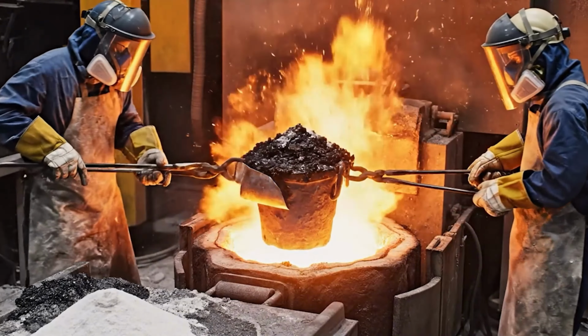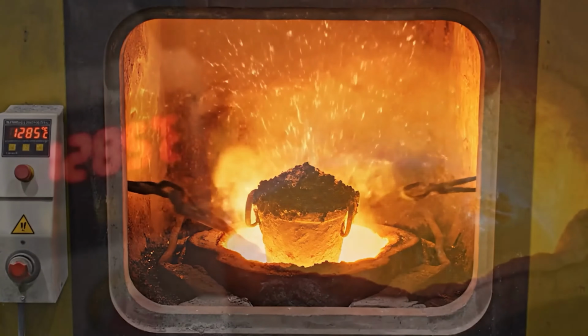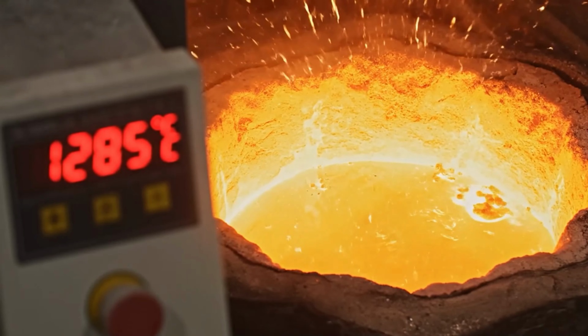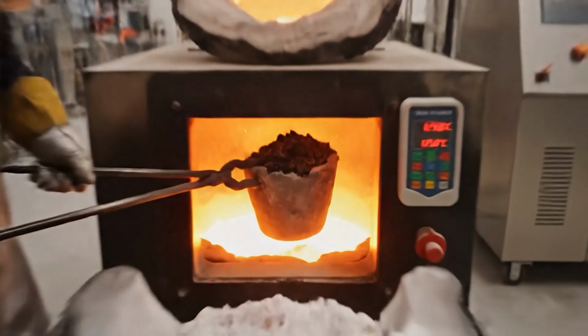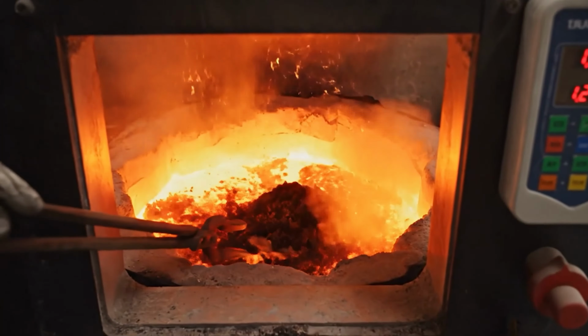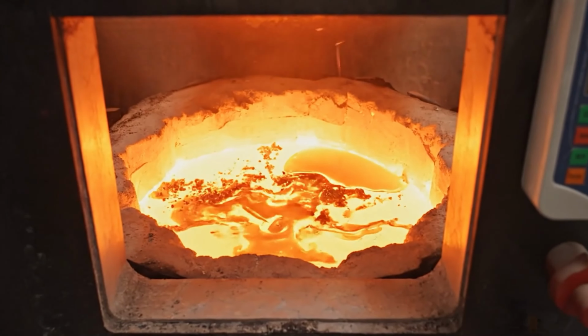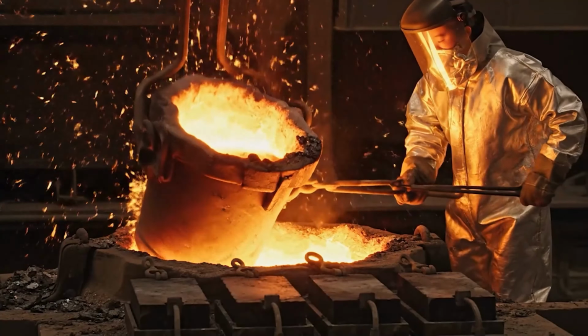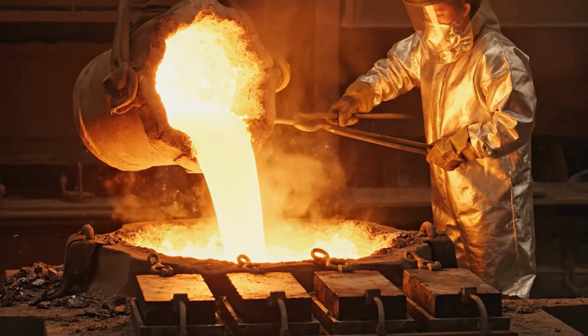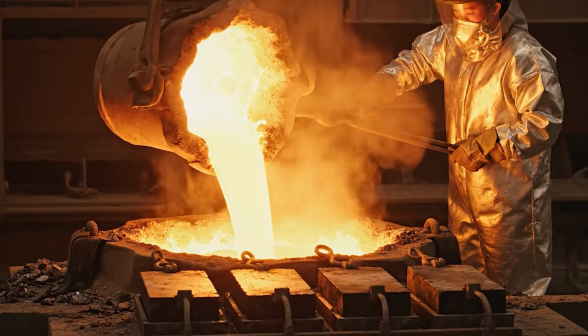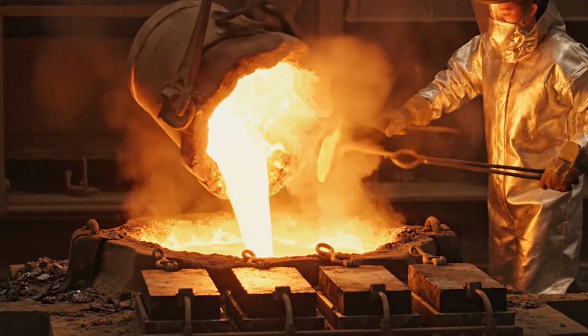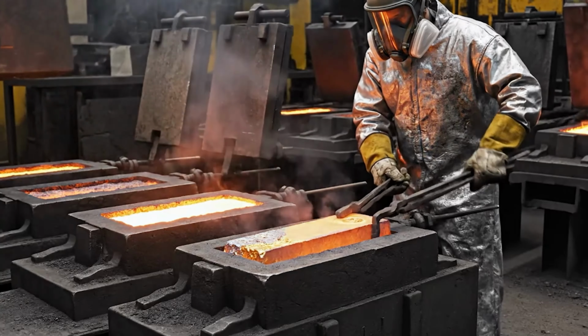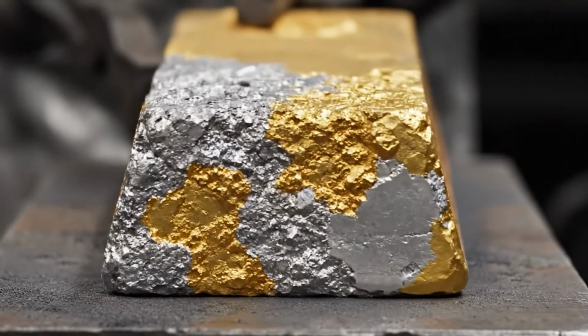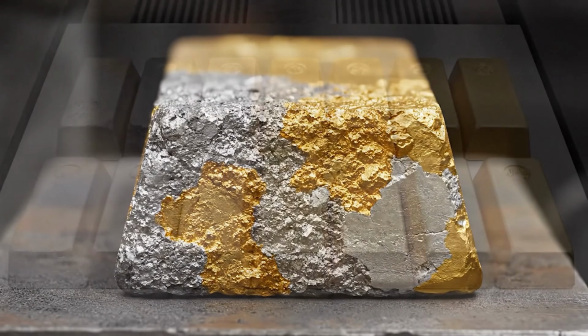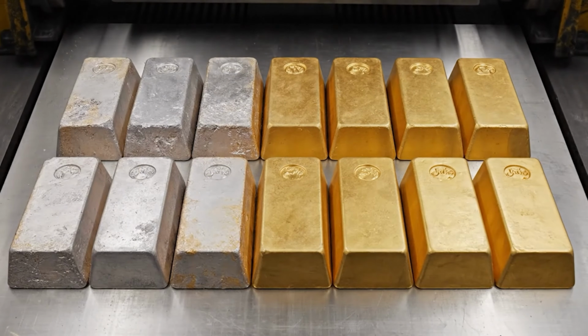In a furnace at 1,200 to 1,300 degrees Celsius, the sludge is melted with fluxes: borax, silica, soda ash. Impurities form slag that's skimmed off. The molten metal, now doré, is poured into molds. Doré bars are typically 70 to 90% gold, 10 to 30% silver, with traces of copper or platinum group metals.